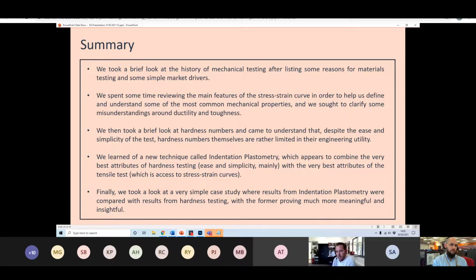And then we adopt just a very simple von Mises yield criterion to drive the plasticity. So it's all driven by deviatoric stresses. Nothing there about hydrostatic stresses, which is why, for example, we can't use our technique on highly porous materials, which compact, and therefore hydrostatic deformation becomes important. Okay, so again, to put it very clearly and succinctly, it is just an inverse FE technique with a von Mises yield criterion and a consistent continuum plasticity equation with a sprinkling of some clever optimization that I can't tell you about. Apologies.